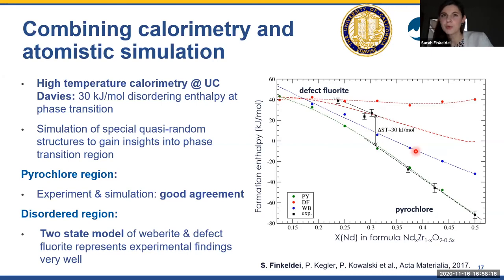So actually we were trying to verify if what we had seen with the neutron diffraction and PDF analysis, we could see any indication of with a different method, this order-disorder transition along different length scales. And what we did is we developed a two-state model that combines the weberite and defect fluorite in the computational studies. This is the dashed red line here, and it describes our experimental findings fairly well.